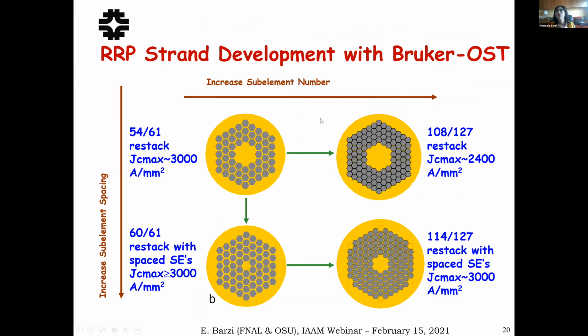So what we did was we worked with industry and specifically with Oxford Superconducting Technology, which now is Bruker, and we asked them, because on one hand we wanted to improve our field quality, and you improve your field quality by reducing the size of your subelements, of your superconducting elements. So you want to go with increasing your subelement numbers. You want to have more of these filaments in the same 1 millimeter size wires, say, to improve your field quality, because as I said, the magnetization curve depends on that size, therefore your field quality. But to reduce subelements, we found out through some studies from experiments that I'm not showing here, that it would help if the superconducting elements were spaced.